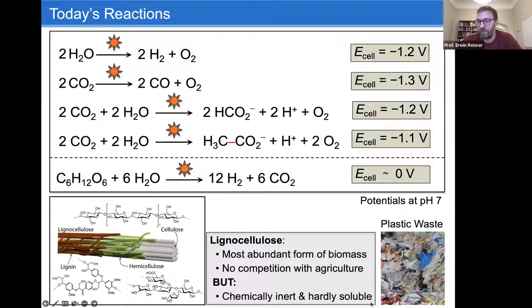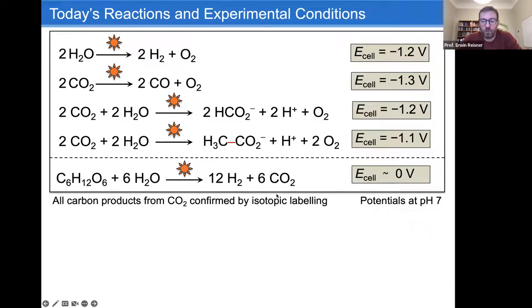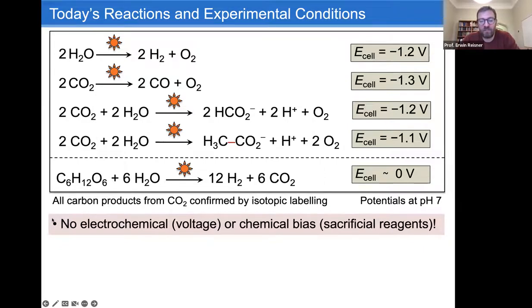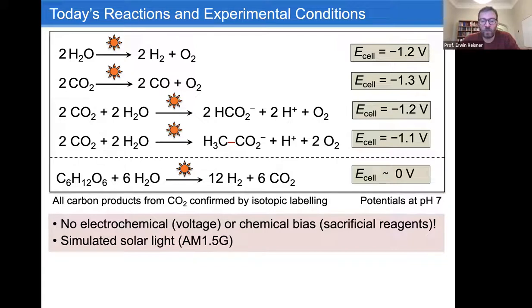We also use plastic waste for the reason I mentioned before. There's still a huge amount of plastic waste being generated that's not recycled and that's either just being burned or being disposed of. So today, what I wanted to say straight away is that all the products I'm showing in the reactions have been confirmed by isotopic labeling to be sourced from carbon dioxide. So they've not only been quantified, but also we know they're really coming from CO2, which I think is very important. None of the systems or devices I will be showing has an electrochemical bias voltage. So these are really standalone devices, and we're also not feeding in sacrificial reagents. So we're always looking at two meaningful half reactions in the chemistry. The light I'm using is simulated solar light, specifically air mass 1.5 global. This just means it really emulates real world conditions on an average global standard.